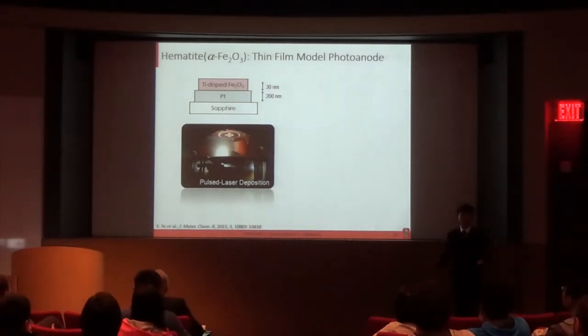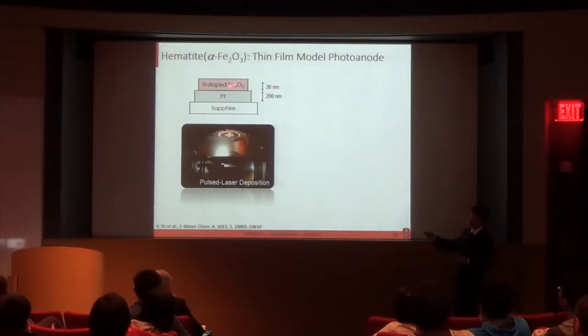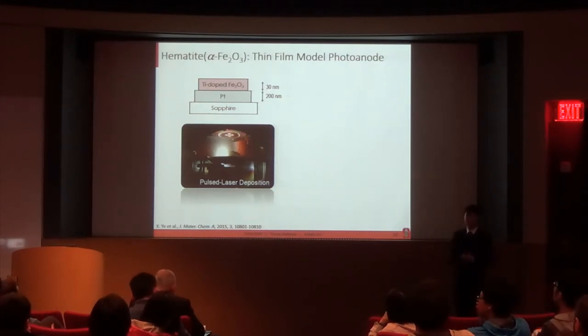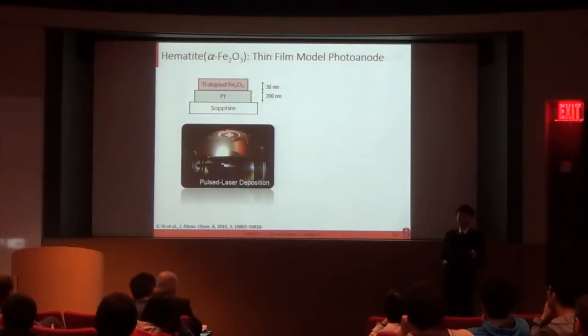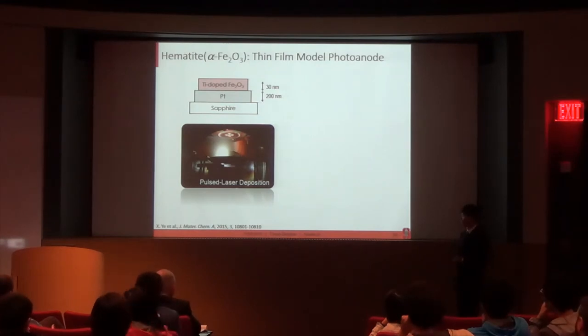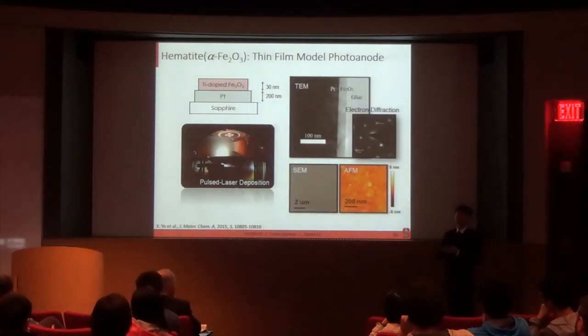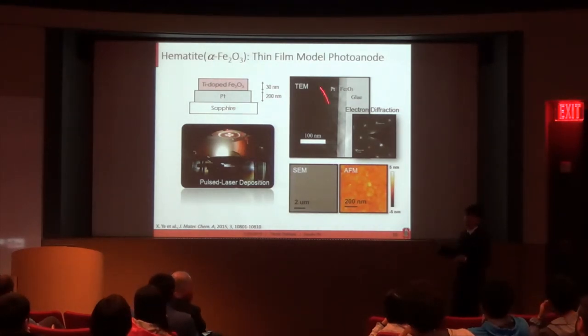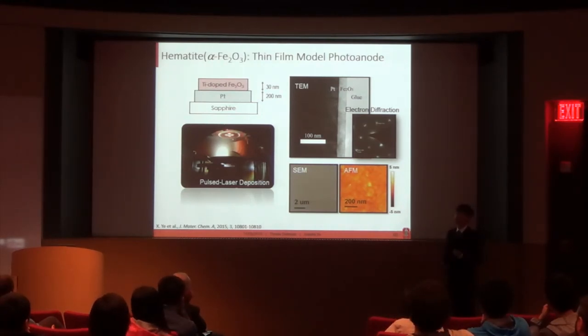For the purpose of fundamental study, I used a hematite thin film as a model system without any catalyst. So this thin film is deposited by pulsed laser deposition, a technique that uses high energy lasers to ablate material from the target and deposit under controlled temperature and controlled oxygen partial pressure. This allows us to achieve very flat and smooth thin films with high crystallinity, as shown in these characterizations. The titanium doping in hematite is to provide sufficient electronic conduction and also makes this material an n-type semiconductor.